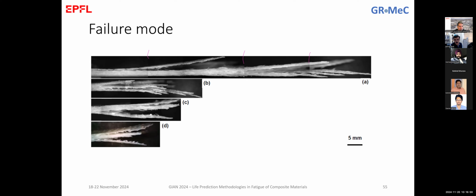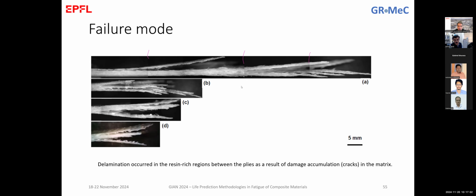What we see in this slide is the delamination that occurred in the resin between the layers. One layer, second layer, third layer, and so on. We had in total 8 layers of material, and we see that during the loading you have a lot of delamination in different places of the material, and this delamination propagates. It is not only localized at the fracture region, but it is propagating to the specimen around the crack, around the damaged area.